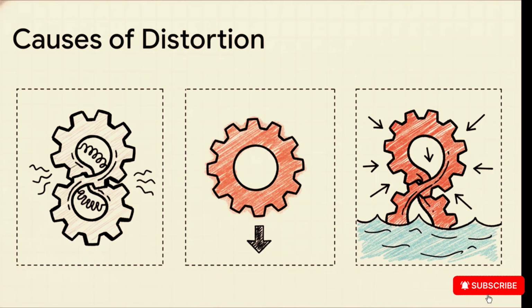So why does the gear warp? Well, it really comes down to three main things. First, you've got stresses left over from when the gear was first cut. When you heat it up, those stresses are released. Second, at really high temperatures, steel gets weaker, and it can actually start to sag under its own weight. They call that creep. But the biggest problem, by far, is the rapid cooling, the quenching. As the steel's internal crystal structure changes to become hard, it physically expands. And if that expansion doesn't happen perfectly evenly, the gear twists and distorts.